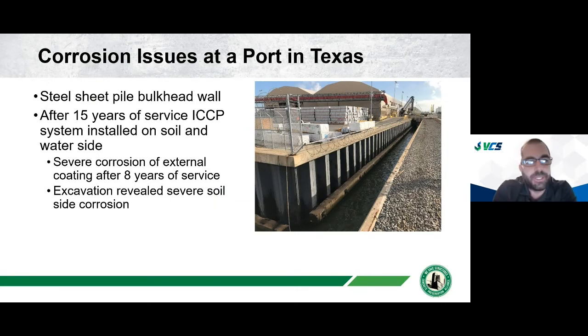This is a corrosion issue at a port in Texas. So it was a steel bulkhead wall, and the bulkhead had been installed for 15 years. They started to see some corrosion, so they decided to install an impressed current cathodic protection system on both the soil side and the water side. And then after 8 years of service with the ICCP system, they were still seeing some pretty aggressive corrosion, and they didn't know why because they had an ICCP system.